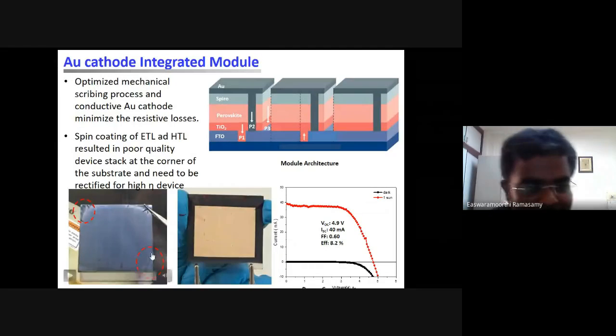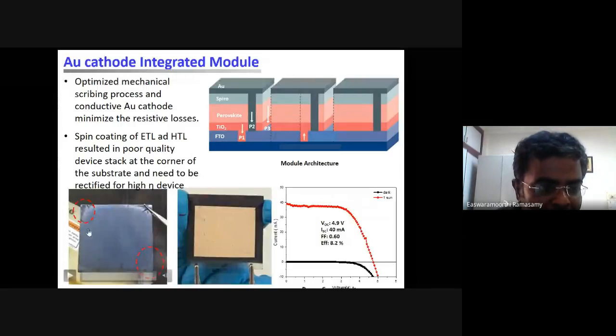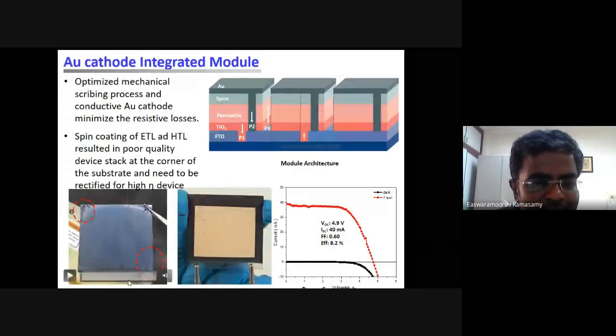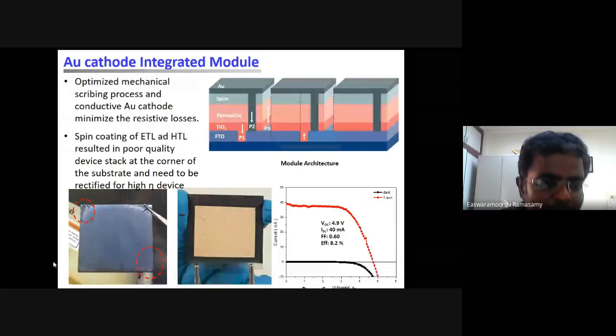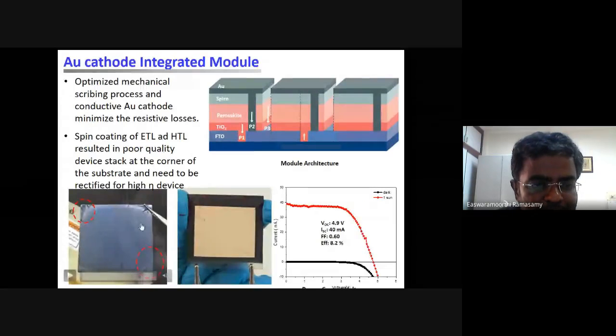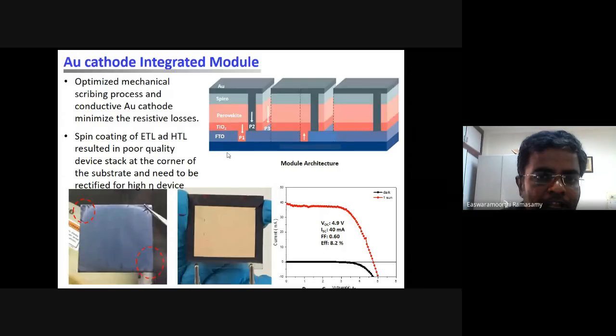You can see that these devices were still not perfect because some edges, like you can see in these dotted circles, are not completely covered with the contacts. That is the problem. Only the middle portion is highly uniform, so the edges were not perfect as we expected. So we developed a new patterning approach, and instead of making a single large area device, we made a serially interconnected concept. So this is a complete device on 50 mm by 50 mm, and we got